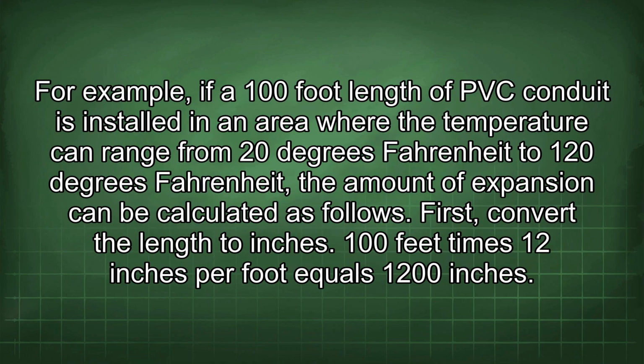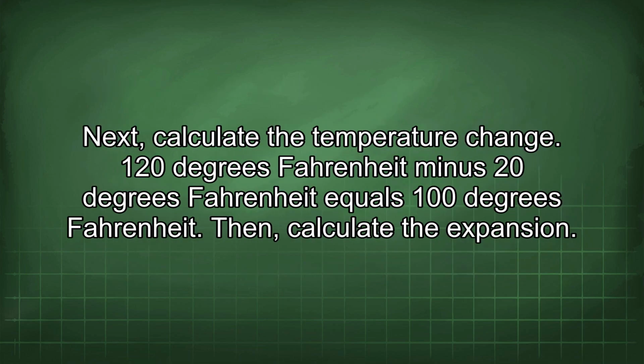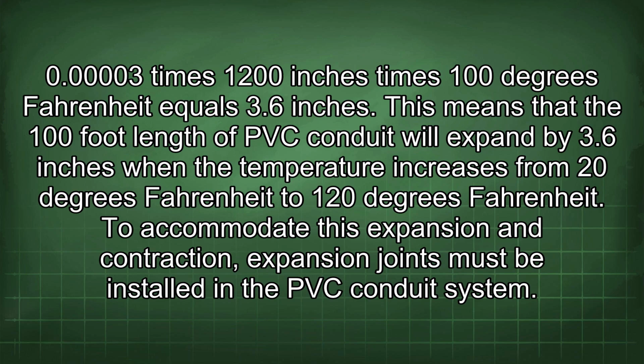For example, if a 100-foot length of PVC conduit is installed in an area where the temperature can range from 20 degrees Fahrenheit to 120 degrees Fahrenheit, the amount of expansion can be calculated as follows. First, convert the length to inches. 100 feet times 12 inches per foot equals 1200 inches. Next, calculate the temperature change. 120 degrees Fahrenheit minus 20 degrees Fahrenheit equals 100 degrees Fahrenheit. Then calculate the expansion. 0.00003 times 1200 inches times 100 degrees Fahrenheit equals 3.6 inches. This means that the 100-foot length of PVC conduit will expand by 3.6 inches when the temperature increases from 20 degrees Fahrenheit to 120 degrees Fahrenheit.